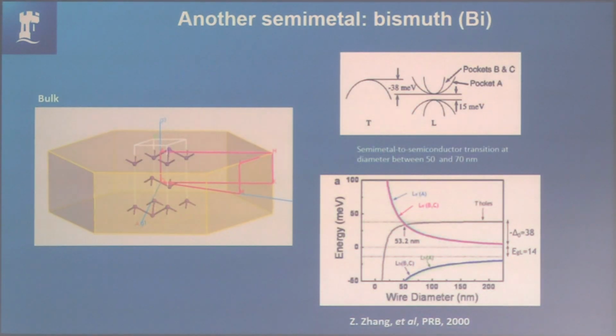There's a lot of challenges that we ran into. So we work with a group in Jülich, where they do a lot of MBE of bismuth telluride, predominantly for topological insulators. But for their test wafers, they make really high quality bismuth. And they give us these test wafers and we try to process them. Now this is also some of the work from Dresselhaus's group and so forth. But bismuth is kind of an interesting material in its own right.